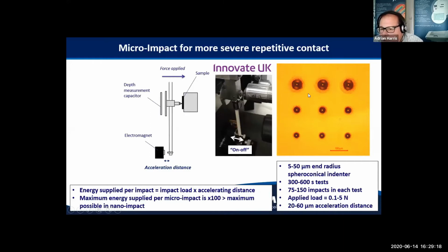So here's some examples on hard cutting tool coating. We tend to use bigger probes. This is another benefit, is that we can use a big probe which itself will undergo less wear than a small probe that we'd use in nano impact. So that's really great because that helps to keep under control the rate at which we consume indenter tips.